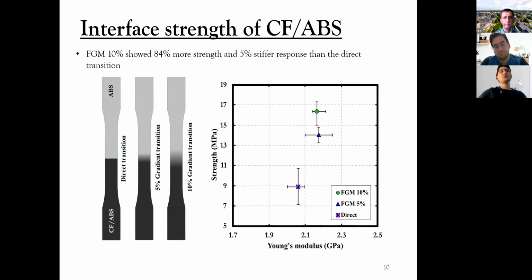Okay, we can also test the lengths of gradient transition as well. The length of the FGM transition increased to 10%. However, 10% is the length percentage of the total length. So if our test sample is 165 mm length, the 10% refers to that length at the middle of the specimen. It shows that if we increase the gradient transition, we get more strength, around 84%, and stiffness 5% as well. Stiffness doesn't change that much, but we increased the tensile strength by 84%.